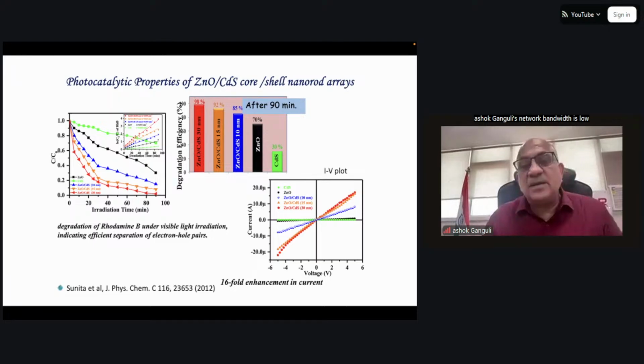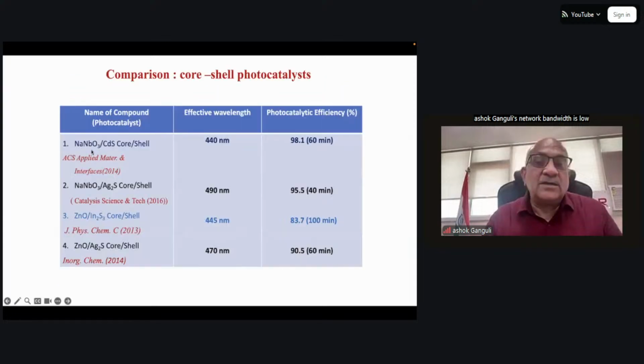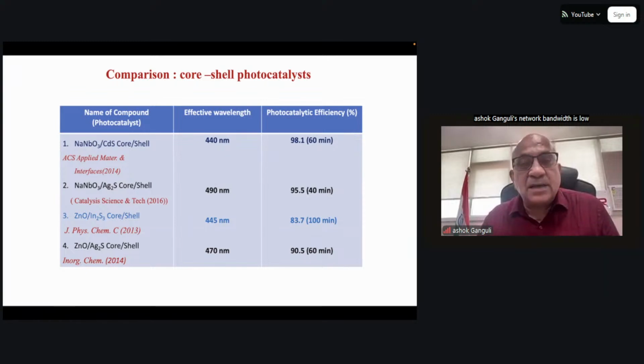Same thing you can reciprocate. You can change from zinc oxide to sodium niobate or cadmium sulfide to silver sulfide to indium sulfide. You can get similar properties. The numbers will change. For example, the effective band gap will change, so the effective absorption wavelength will change. The photocatalytic efficiencies will change. The photocurrent will change. But all of them show improvement because of the formation of the mid-band gap semiconductor as a shell on top of the UV photocatalyst, which is zinc oxide or sodium niobate.